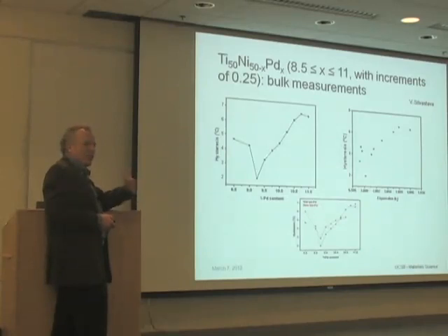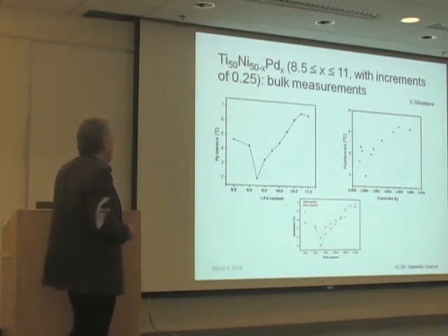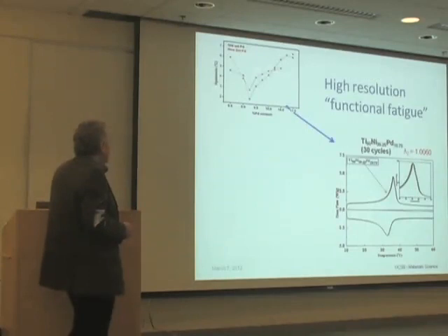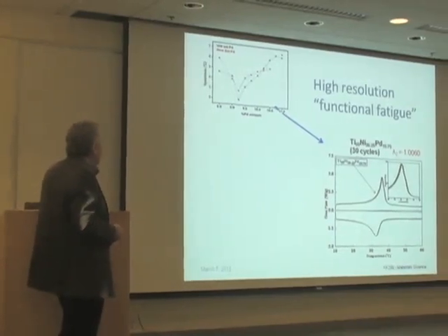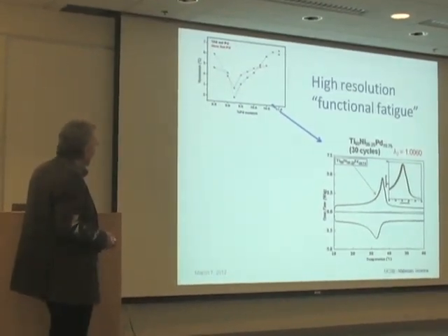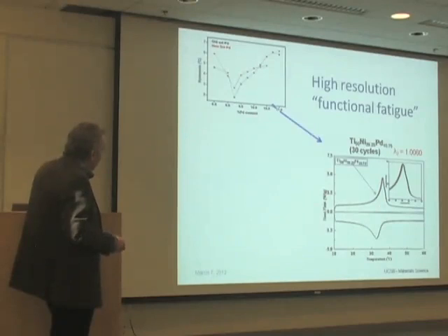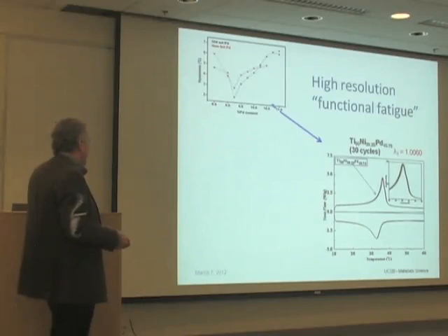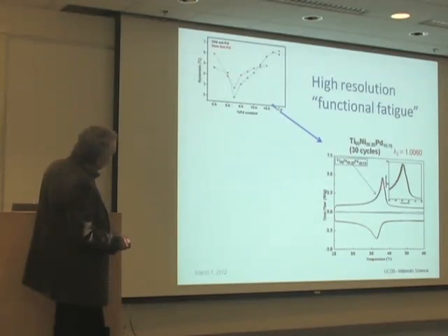Okay. Now, what matters more for energy conversion is this. So this is DSC, calorimetry, and I'm heating and cooling. And there's a peak here, which is the heat absorbed, the latent heat for one direction of phase transformation. I guess that must be the heating direction, and this is the cooling direction, yep. You can see that there's a kind of thickening of this. And it's a little bit of a blow up here. It's not very clear on the screen. I'll show you a blow up again later.